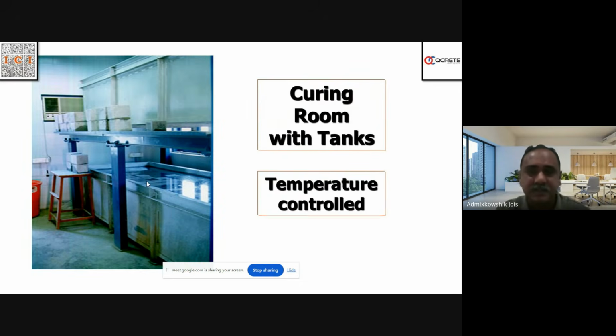It has to be properly made, where you use thermostats in winters to heat the water in low temperature situations, and in summers you run AC, so that the water temperature is 27 plus or minus 2 degrees. In India it is 27 plus or minus 2 degrees. In USA it is 23 plus or minus 2 degrees. In England it is 22 plus or minus 2 degrees, or 20 plus or minus 2 degrees. Like this, each standard has a specific temperature range where it has to be cured.